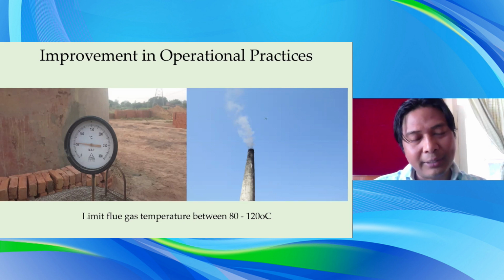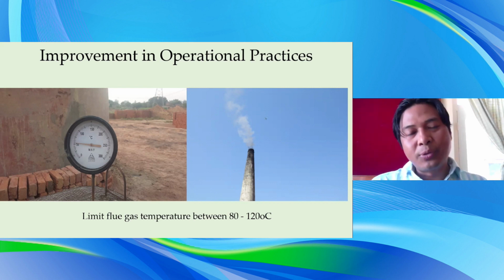flue, the kiln. So if the temperature is above 120 degrees, the hot gas which can be used to dry out the green bricks in the preheating zone is passed out. So if it is below 80 degrees, then the tendency of getting accumulation of water vapor inside it becomes high. So the most efficient design, most efficient operation is if the flue gas is maintained within 80 to 120 degrees, then it is the most efficient design of the kiln, operation of the kiln. So we did that, and we just try to maintain this temperature within the firing.